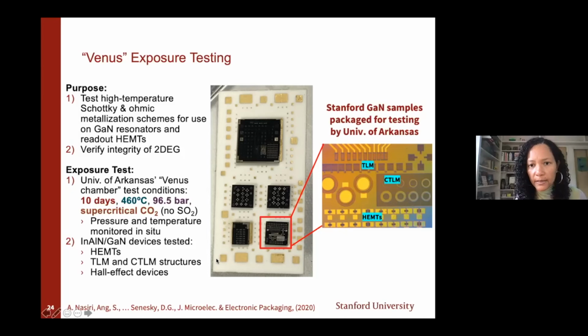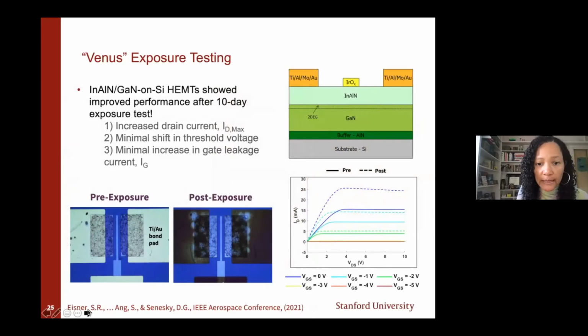To simulate how these guys would work in a Venus-like environment, we immerse them in something called a Venus chamber. This was at University of Arkansas, and we're actually bringing one up in my group right now. We immerse these in Venus conditions for 10 days, so 460 degrees Celsius, 96 bar, supercritical CO2. Unfortunately, it does not have the sulfur dioxide content that you would see in Venus, so it's not the full picture. Actually, CO2 is quite inert. The sulfides are really the constituents that are important in survivability. So these are the things we're gearing up to do at the NASA Glenn Venus chamber, and we're again trying to have these in situ tests. We're working with Tomas Palacios' group to create the experimental plan so we can test these guys live inside of the NASA Venus chamber.